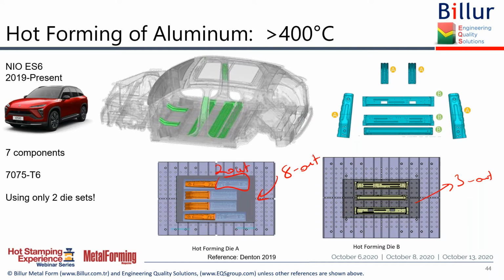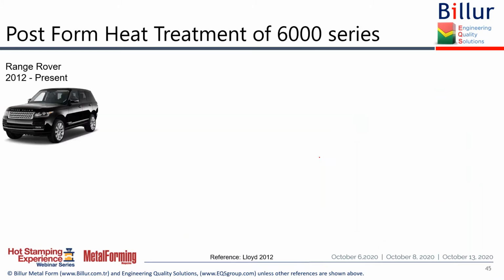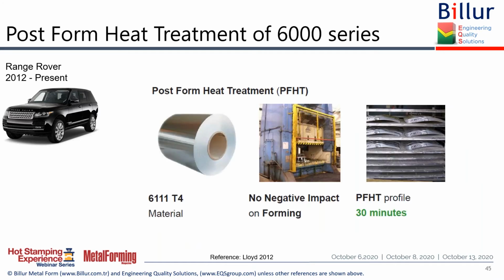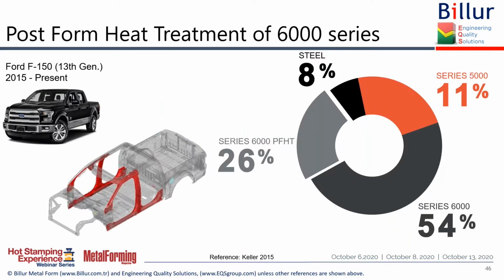And last, this is not heat-assisted forming, but since 2012, what we're also doing is we cold form aluminum 6000 grades, and then we post-form heat treat them. And this has been used in Ford F-150 as 26% of the cab weight from PFHT grades, 6000 series with very, very high strength. It can exceed 300 megapascal in yields.